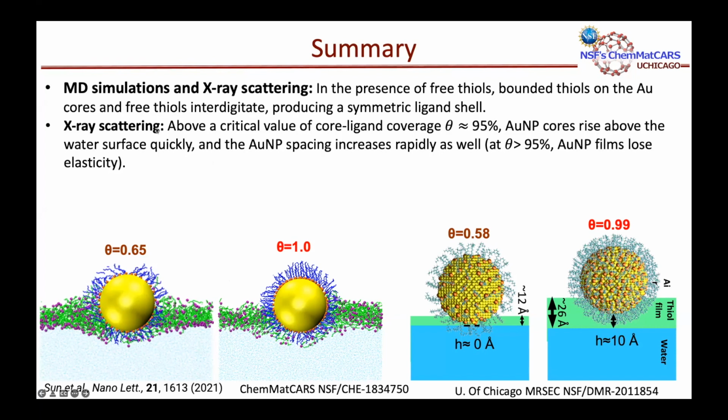And in addition, the X-ray scattering shows there is a critical value of about 95%, above which the gold core separations become very large, and the gold nanoparticles move away from the surface water.